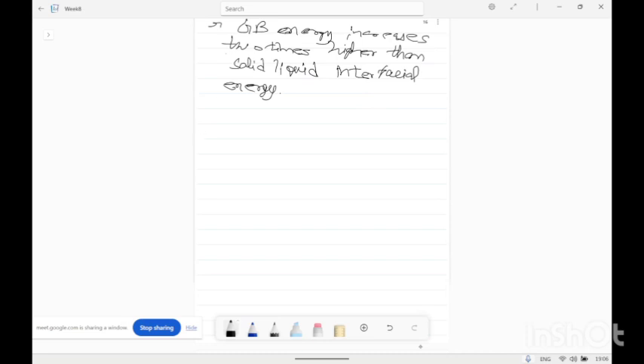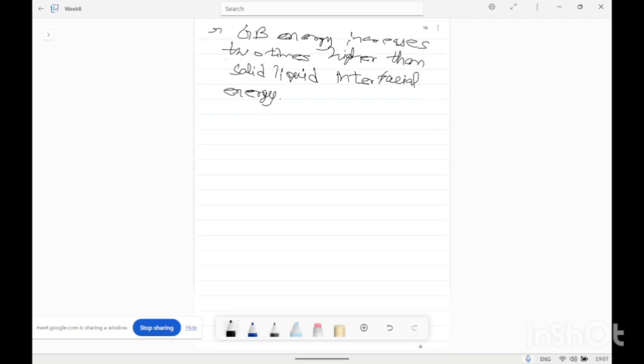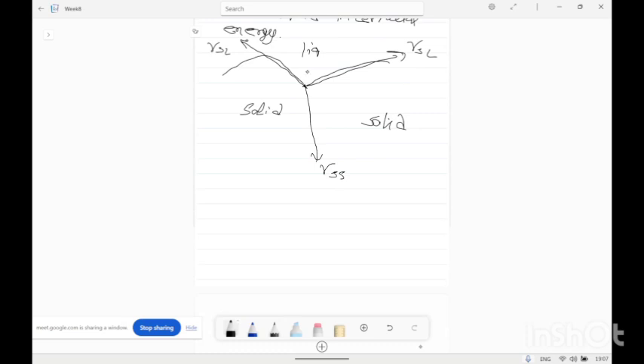So in the infiltration process, the relative motion of liquid and solid phases leads to the formation of a curvature. Like if we see two solid regions, one grain, this is solid, and above this is liquid. So the surface energy of this curved surface can be written as gamma SL, and the surface energy between two grains can be referred to as gamma SS, and the angle between these two curved grains is represented as phi, and phi is the dihedral angle.